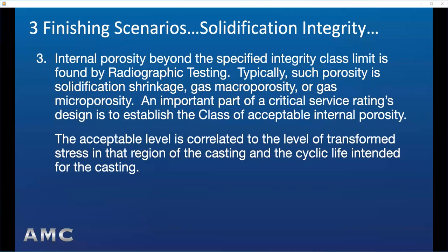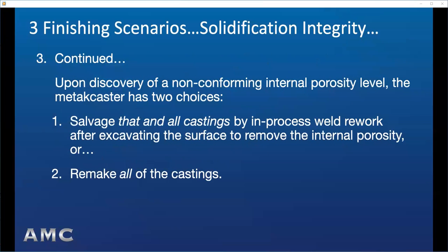Part of a critical service casting's design is to establish the class of acceptable internal porosity. The acceptable level is correlated to the level of transformed stress in the region of the casting and the cyclic life intended for that casting. Upon discovery of a non-conforming internal porosity level, the metal caster has two choices: one, salvage that and all castings by in-process weld rework after excavating the casting to remove the porosity, or two, remake all of the castings. That choice is typically made on the basis of cost and lead time.